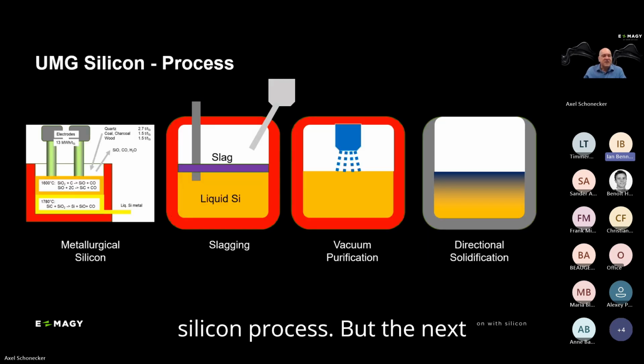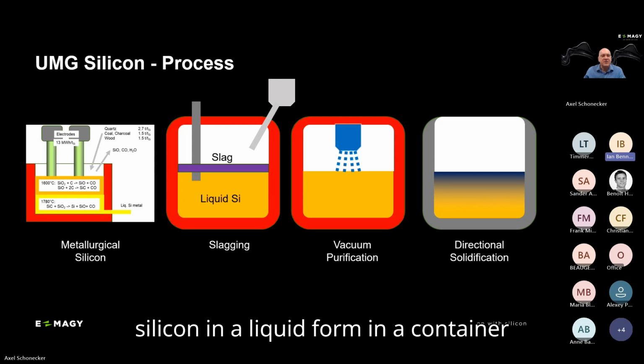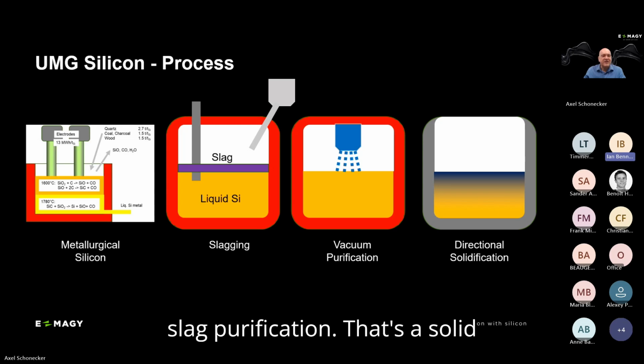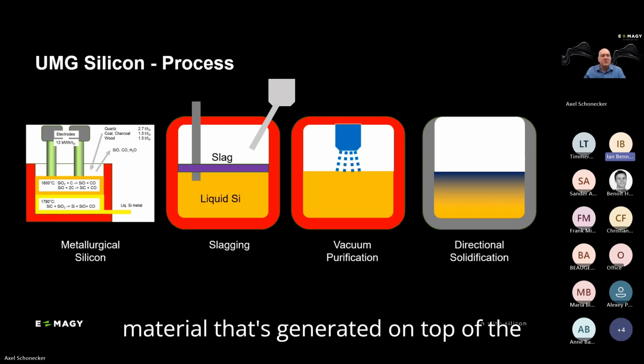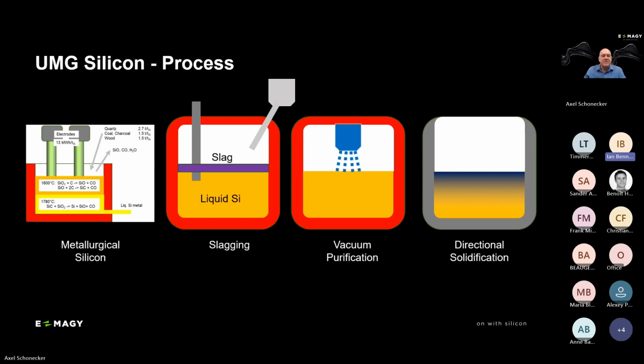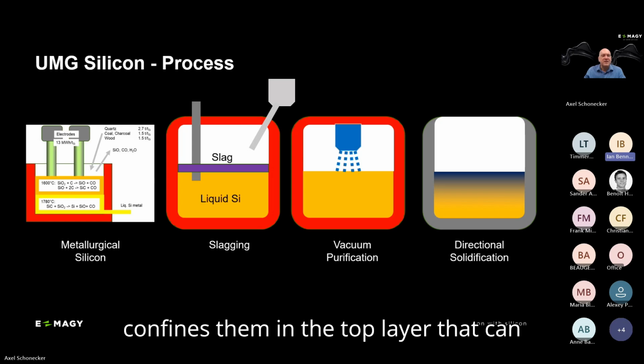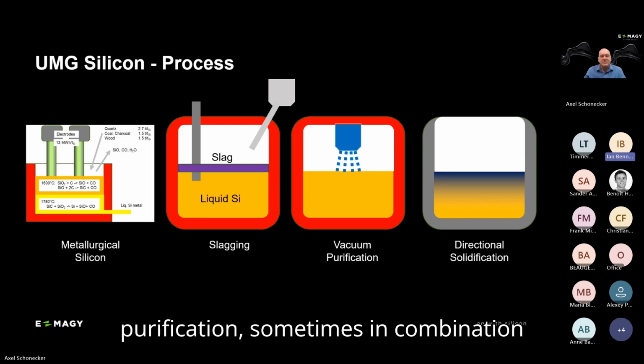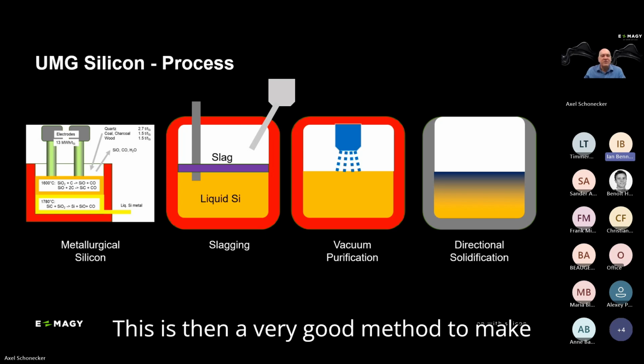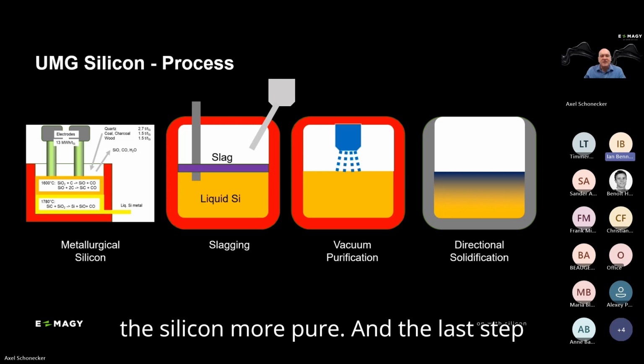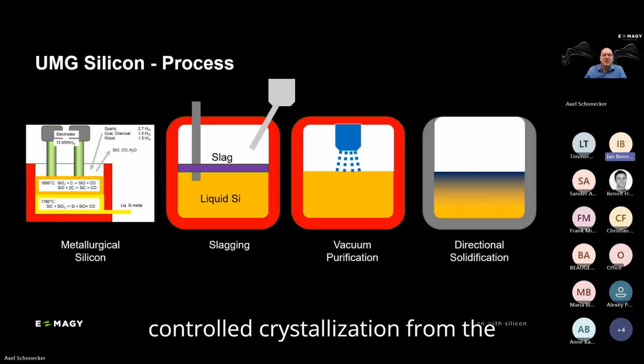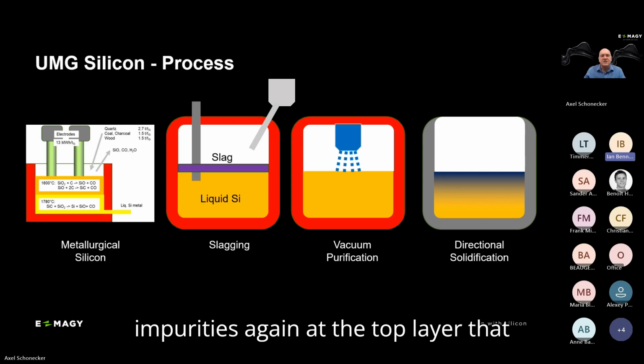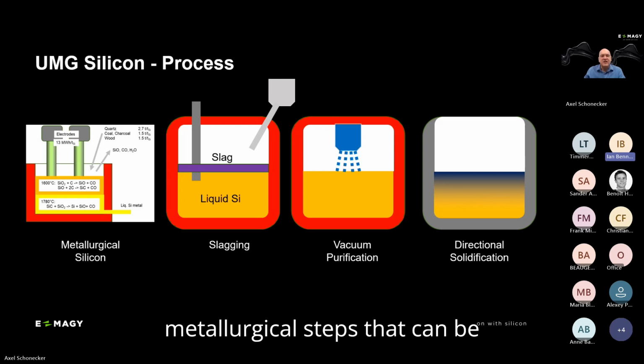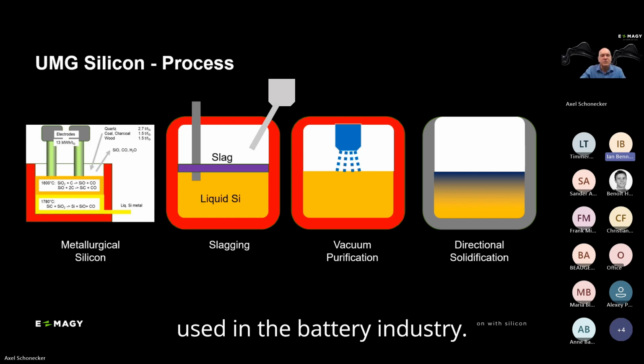Again, it starts with the metallurgical silicon process, but the next steps are all based on melting silicon in a liquid form in a container. And purifying, for example, by doing a slag purification. That's a solid material that's generated on top of the liquid silicon that reacts with some of the impurities and confines them in the top layer that can be removed. Vacuum purification, sometimes in combination with a plasma torch, when impurities have the tendency to evacuate. This is then a very good method to make the silicon more pure. And the last step is a directional solidification. That's a controlled crystallization from the bottom upwards, which typically drives impurities again in the top layer that can be removed. So these are metallurgical steps that can be used to get silicon clean enough to be used in the battery industry.